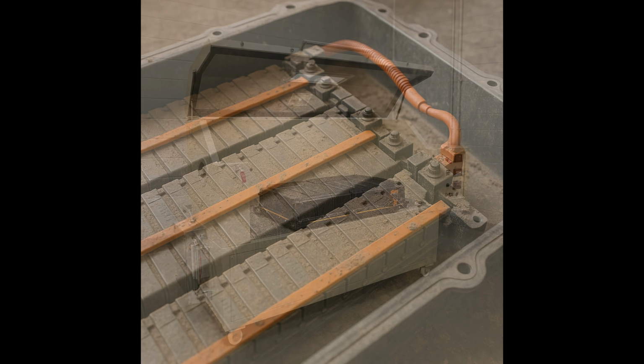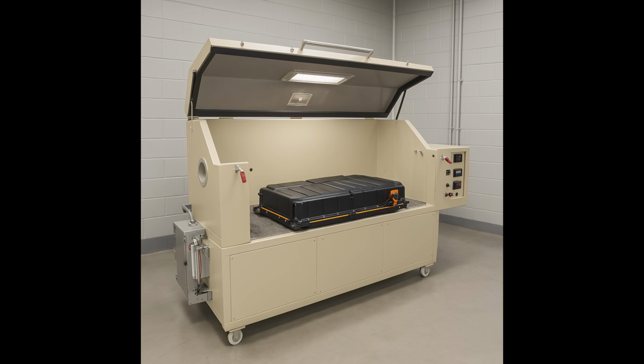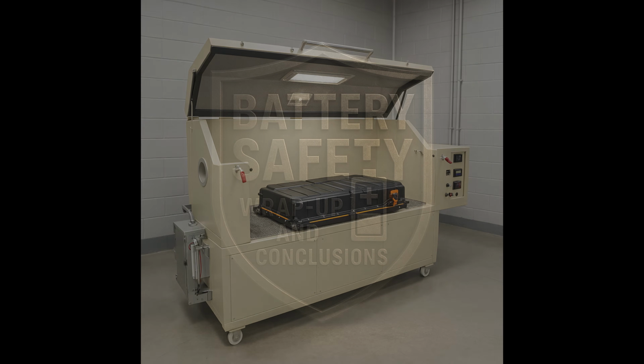Real-world risks of dust ingress include high-voltage arcing from conductive dust particles, corrosion and signal degradation at sensor and connector interfaces, seal erosion from long-term abrasive action, and false BMS triggers due to contaminated sensors such as pressure and humidity sensors. Dust doesn't cause an immediate failure, but it can cause eventual failure, and that's why this test matters. Design considerations include proper IP-rated grommets and cable glands, multi-stage labyrinth seals to deter particle entry, pressurized equalizing membranes that block particles but allow gas exchange, and hydrophobic and oleophobic coatings for exposed surfaces.